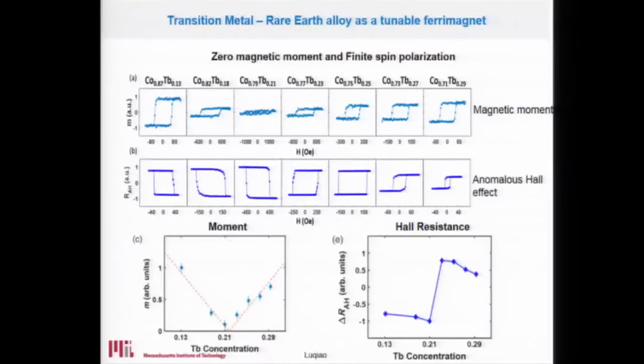But at the same time, if we measure the electrical property, which is the anomalous Hall effect, you can see that even when the moment reduces to zero, you still have finite Hall resistance. So that means you have zero moment, but a finite transport related property. And you can utilize this transport property to tell whether the material is located in state 1 or state 0. And here state 1 can be defined as cobalt pointing up, and state 0 defined as cobalt pointing down. And terbium is just chosen the opposite direction with cobalt. Room temperature, yes. And also you can see that the moment variation is summarized in this figure.